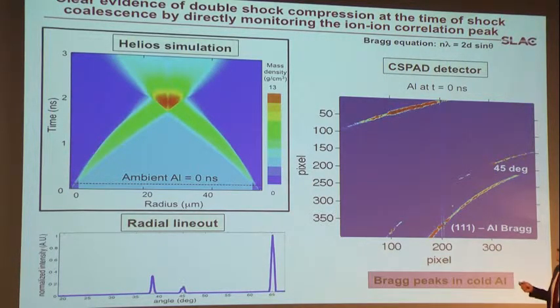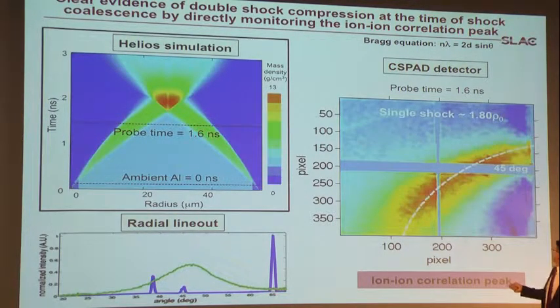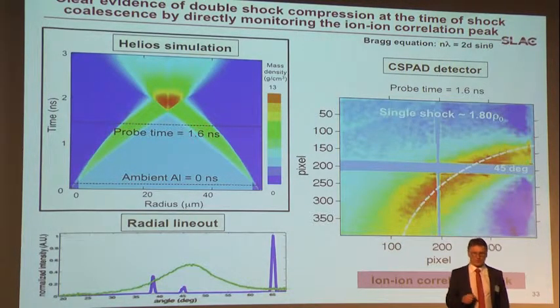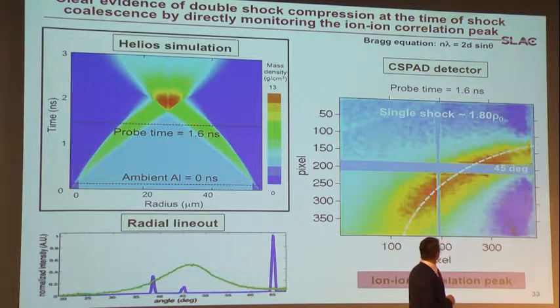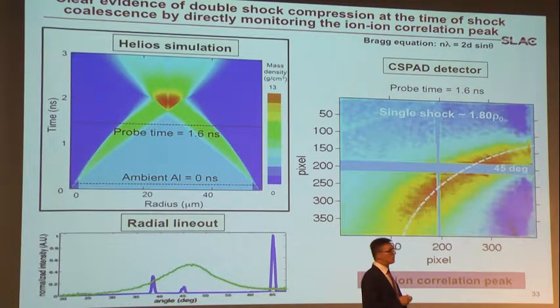this regime. So this is a simulation of the two shock waves as they propagate through our solid. And when we do X-ray scattering of that, we see the Debye-Scherrer rings, and this is a 1-1-1 diffraction peak, for example, in aluminum at T equals 0. And as the shocks are propagating, we measure a broad ion-ion correlation peak. Now, this is wave number resolved scattering. So although there is no lattice anymore, the Bragg equation still holds. So we don't have a 3D lattice spacing. Instead, we have an average distance between ions.